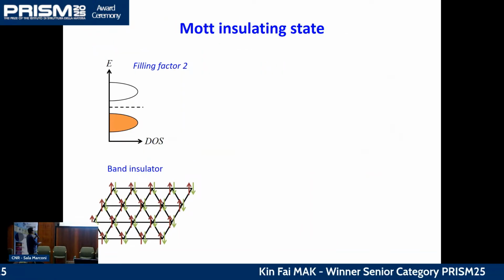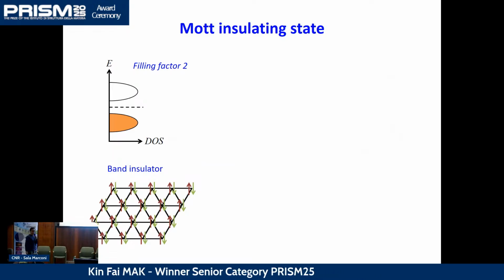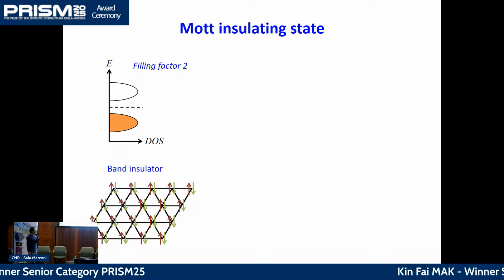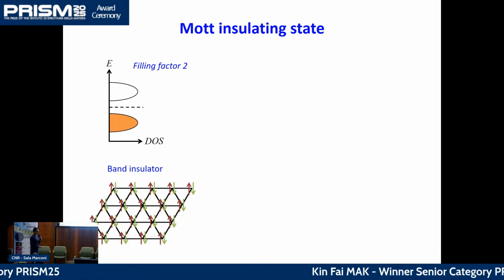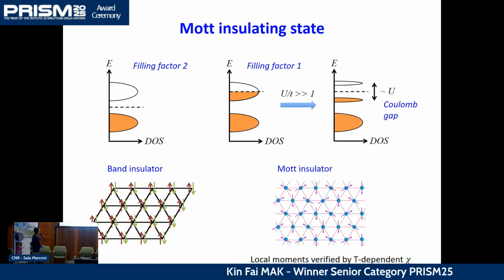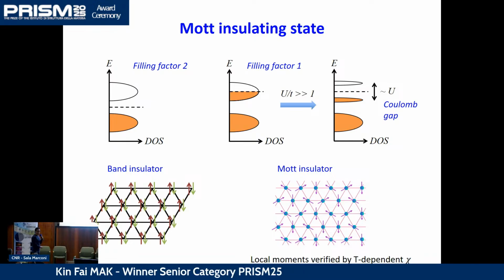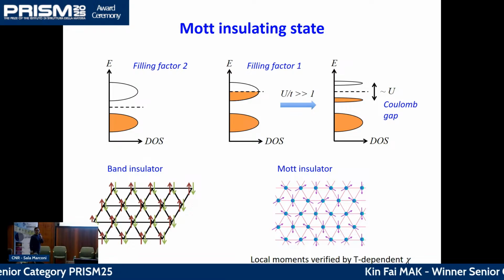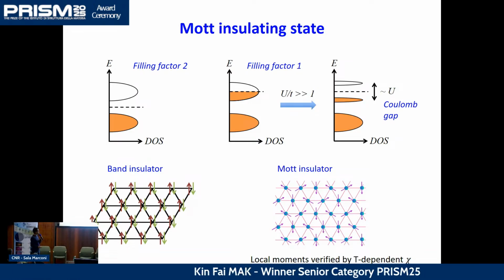If you have a filling factor 2, you have 2 electrons per site, and that corresponds to a fully filled band. Then just by band theory, it's an insulator. It's just a band insulator. It's an insulator due to the Pauli exclusion principle. On the other hand, if you have filling factor 1, which corresponds to 1 electron per site only, that corresponds to only a half-filled band. Without any interaction, it should not be an insulator. The band theory tells you that it should be just a metal.